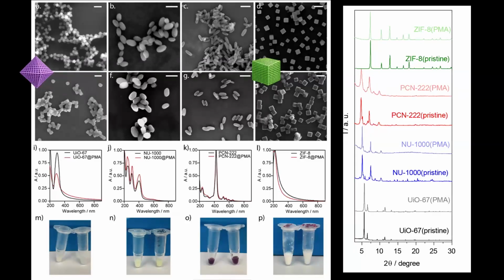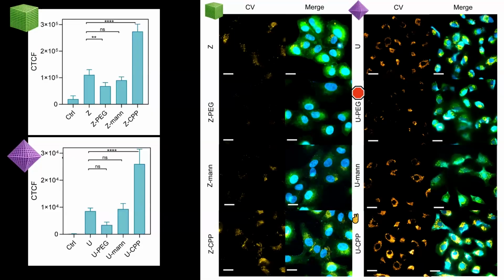She has these nanoparticles, either with this octahedral structure like UIO, this rice-like structure like NU, or this PCN222, or this ZIF-8. ZIF-8 is the one that we use from the beginning with the polymer, and then we do the encapsulation. When we do the encapsulation, we preserve the structure properties, optical properties, and so on, by X-ray, by BET, and so on. And then I asked her to compare internalization. So this is what we were doing 15 years back. So putting the same gold nanoparticle in different coatings, and see which one is better to bring into cells, or to escape an endocytic route, or to do whatever.